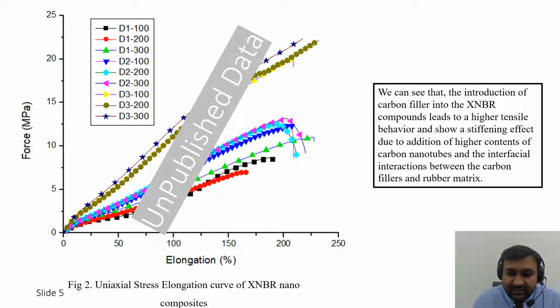So these are the tensile tests which were performed at three different strain rates of 100 millimeter per second, 200 millimeter per second, and 300 millimeter per second. And we can see that the introduction of carbon filler in the XNBR compounds leads to a higher tensile behavior and shows a stiffening effect due to the addition of higher contents of carbon nanotubes and the interfacial interaction between the carbon fillers and the rubber matrix.